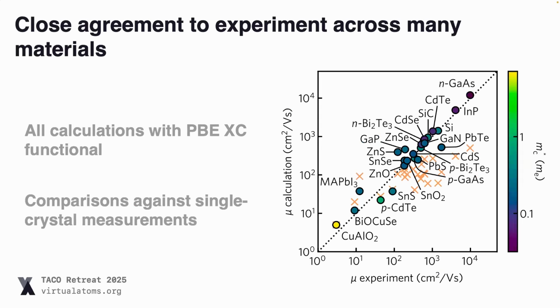Okay. And again, this is just some results that we did across a wide range of materials, showing that we can basically reproduce the experimental mobility for single crystals across a wide range of compounds, even for some very low mobilities like copper aluminium oxide, where you're right on the border of carrier hopping versus band-like transport. It seems to do reasonably well.